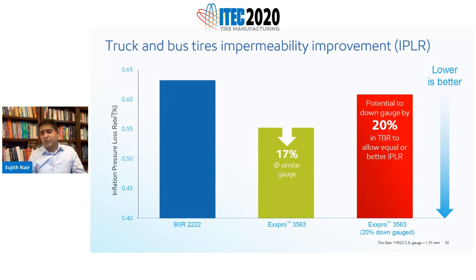Now, one thing that I told earlier is that Exxpro not only allows you to get better performance. Yes, if you keep the gauges the same, your performance is going to be better. But one thing that Exxpro allows you to do is lightweight. So this is the IPLR results from a TBR trial, a truck and bus radial tire, where you can see that the inflation pressure loss rate of an Exxpro based tire is around 17% better than the bromobutyl based tire at the same thickness.